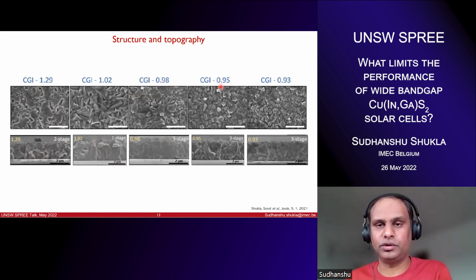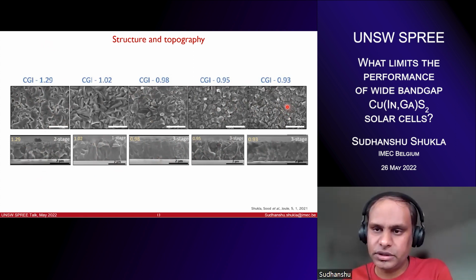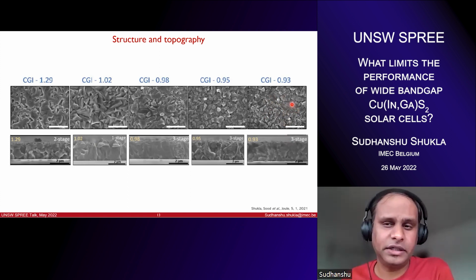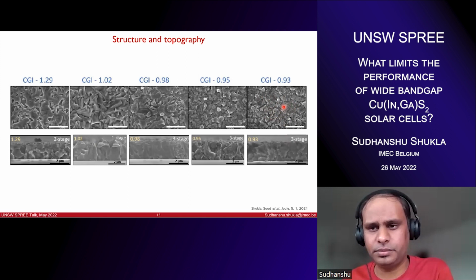And then as you move on to the 3-stage films, as you reduce the copper content, the films look more or less grainy, and some features start to appear at the surface also. These step-like features are very striking. If you look at all the high efficiency, especially co-evaporated papers, those at least beyond 10%, you do see these features. And these features were also talked about recently in a copper indium disulfide study from Princeton, from Professor Kahn's group.